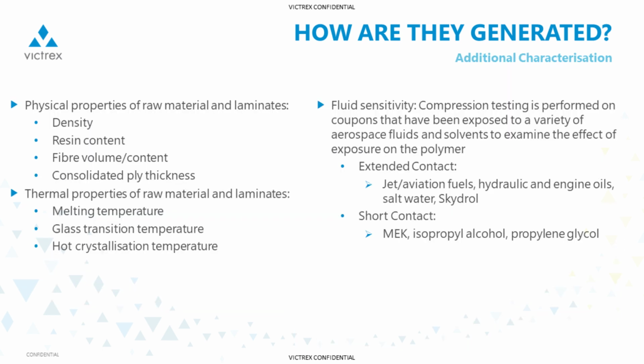In addition to mechanical testing, physical properties and thermal properties of the materials are also measured, such as density, resin content in both the unconsolidated and consolidated material, fiber volume and content, and expected consolidated ply thickness. Thermal properties of thermoplastic polymers that are given in these allowables programs include melting temperature, glass transition temperature, and a hot crystallization temperature.